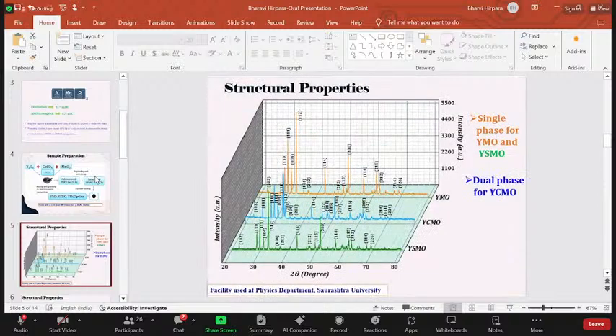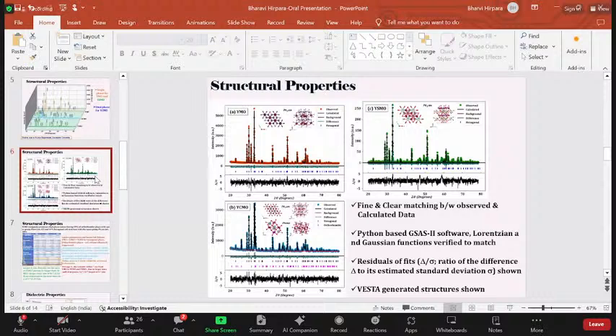The samples have been characterized first for structural confirmation by the X-ray diffraction method. The X-ray diffraction shows a single phase for the YMO and YSMO samples, and as you can see, between 30 to 40 degrees, we can see a dual phase in the middle blue colored YCMO sample. The dual phase exists for two kinds of structures, orthorhombic and hexagonal. For confirmation of that, we have gone through Rietveld refinement of the samples. Here A is the YMO, B is the YCMO, and C is the YSMO sample. We can see a fine and clear matching between the calculated data and the observed data via Rietveld refinement.